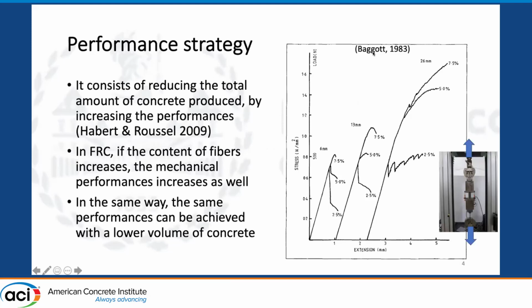One of the first results given by Baggott in 1983 from uniaxial tensile test on different FRC. In particular, he changed the length of the fiber with the same diameter, and with a single length, he used a different percentage in volume of fiber. As you can see, by increasing the percentage of fibers, you increase the strength as well. In particular, when you have long fibers, by using 5% in volume, you reach a strength which is about twice the value that you have when 2.5% in volume of steel fibers is used.